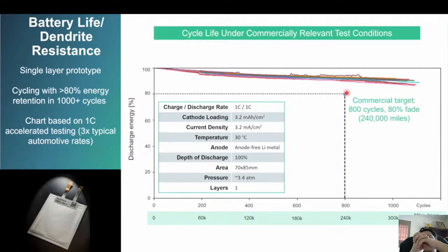Why 800 cycles? If you have a long range electric car of say 300 miles, then if each cycle is a 300-mile range, then 800 cycles give you 240,000 miles. That's pretty considerable to 80% fade. And so then this is showing batches of our cell performance here going out to over 1,000 cycles, cycling quite well under conditions that are listed in this table here.